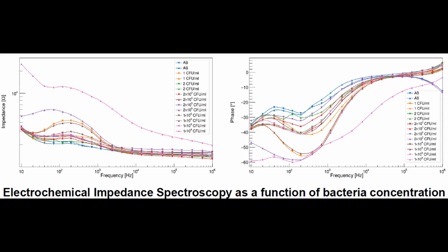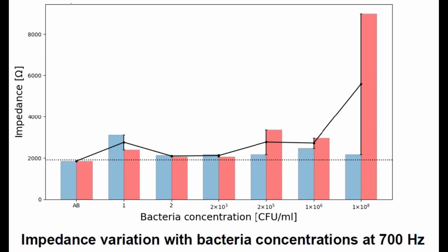Subsequently, the graphs present the detection experiment outcomes. The left graph depicts frequency versus impedance magnitude, while the right graph illustrates frequency against phase. As observed, the phase of most of the samples exhibits a similar behavior, indicating a consistent biosensor effect across all samples. Impedance curves follow similar paths, but magnitudes at low frequencies differ, implying the biosensor effectively detects bacterial presence by altering impedance values. The final graph shows impedance values of the sample at 700 Hz.